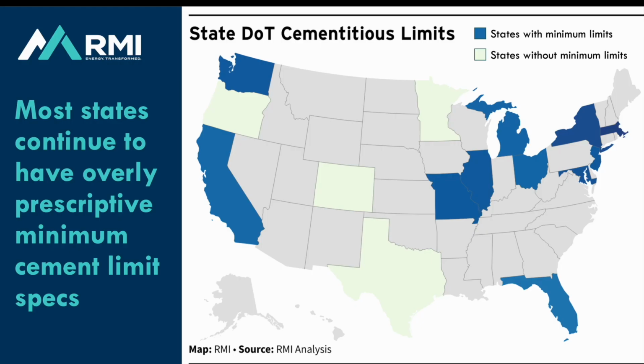Next slide. We found that most of the 15 states we assessed continue to have overly prescriptive minimum cement limits in their specifications. The map shows the states we've assessed. States highlighted in blue all have minimum cement requirements, while those in cream do not have minimum cement limits. Next slide.